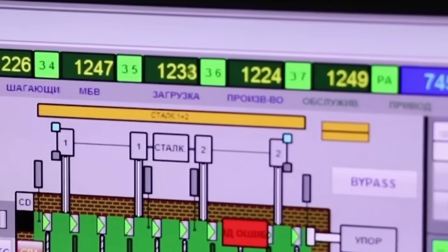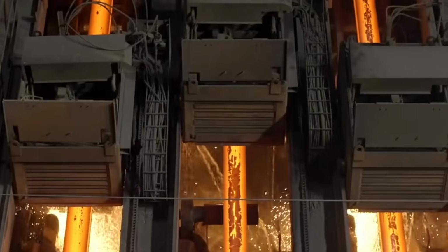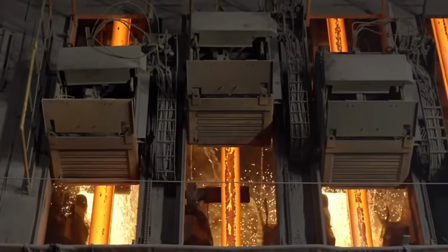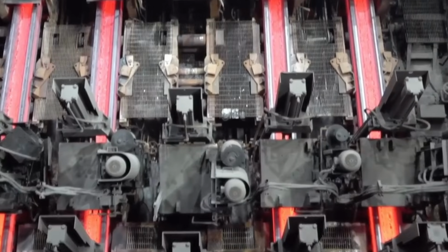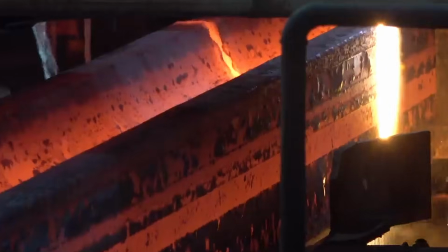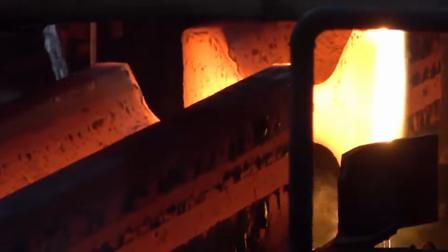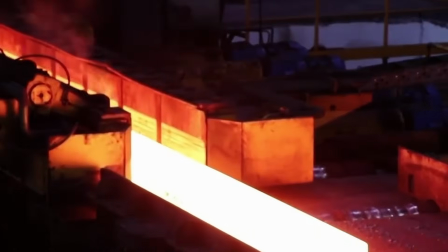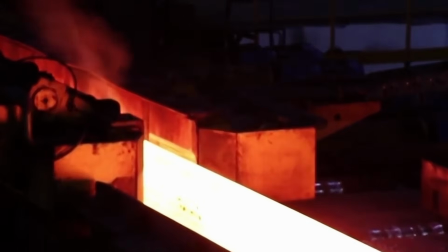The hot beam travels onto a cooling bed with hundreds of steel bars that support while allowing air circulation. Fans blow ambient air across the beam, gradually reducing temperature over 20 to 30 minutes. Cooling must happen slowly and evenly to prevent warping or internal stress. Some mills use controlled cooling patterns, where different sections cool at different rates for specific strength properties.